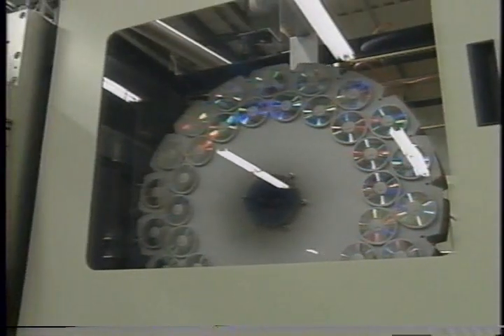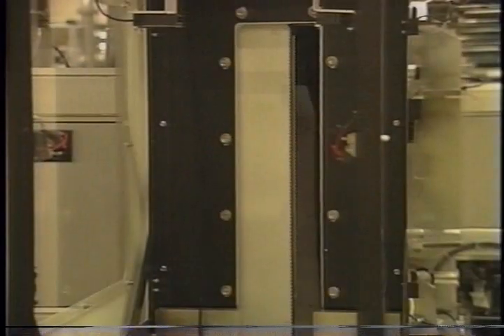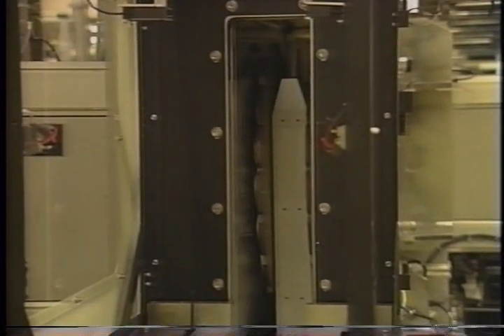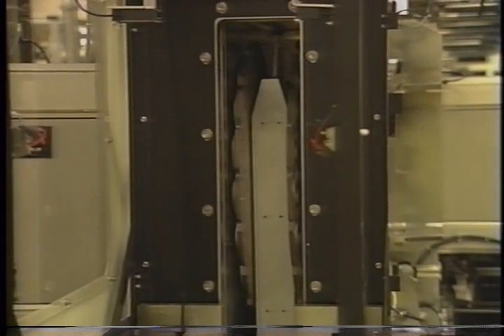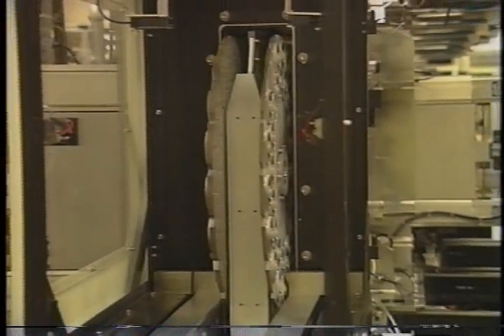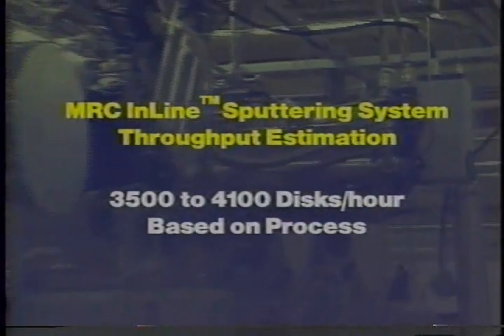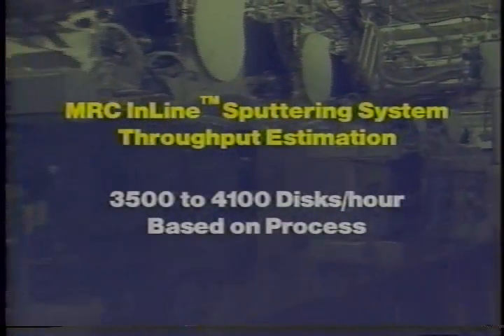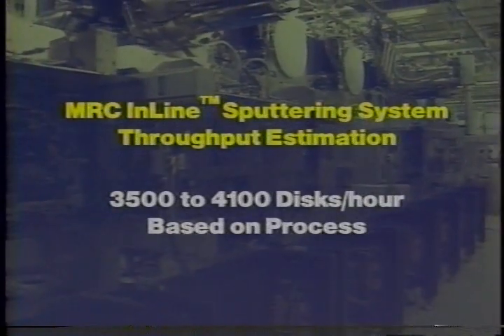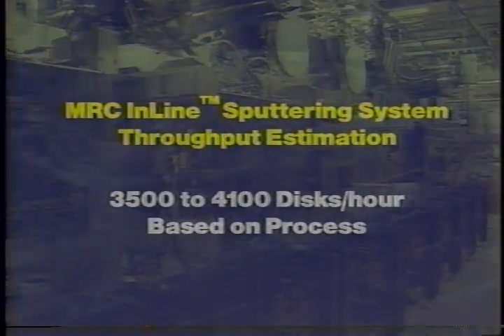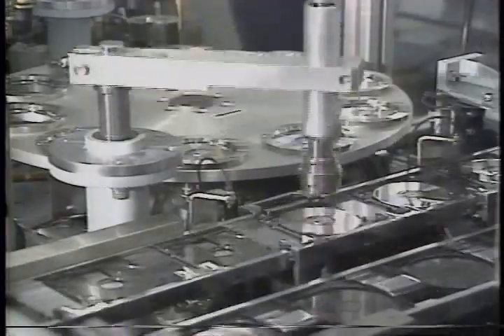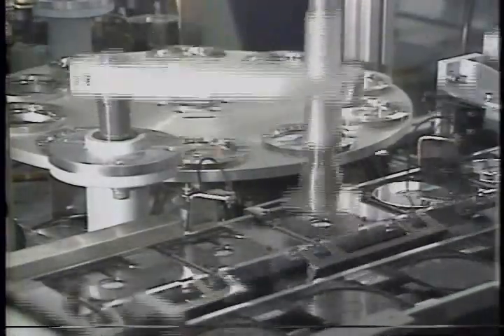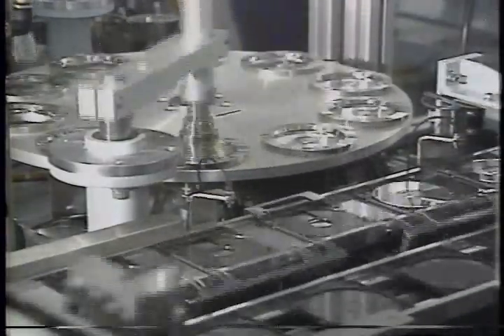As a result, total cycle time has been reduced to less than 90 seconds, generating a throughput of about 4,000 discs per hour. This figure is improving as our mini-disc experience grows. At over 4,000 discs per hour, we've got the fastest mini-disc sputtering system in the world. This is it. The high volume you'll need for mini-disc sales that will soon pass from thousands to millions, and then promise to grow from millions to billions.